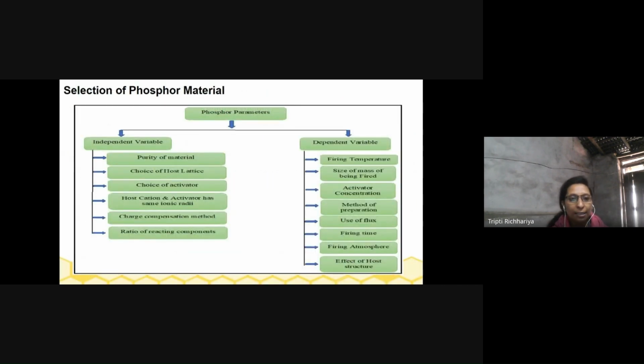So in order to prepare an efficient phosphor, there are some parameters that should always be kept in mind, so that the synthesized phosphor will be highly efficient. These phosphor parameters are broadly categorized into two categories. The first one is the independent variables, those variables which are totally independent from each other. These are the purity of material, the choice of host lattice, activators, and so on. The other parameter is the dependent variable, which depends on each other. For example, the firing temperature and the firing time depend on each other.